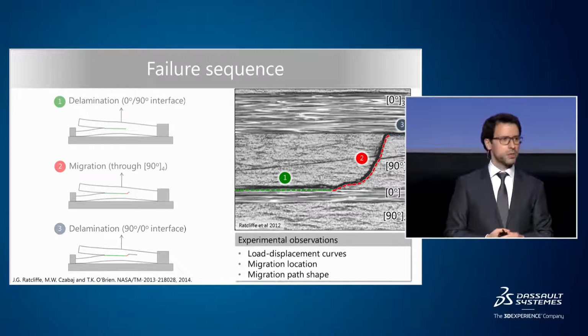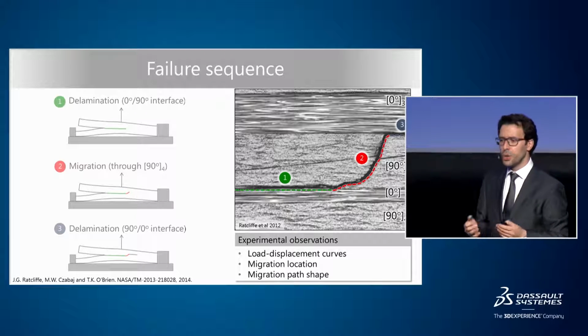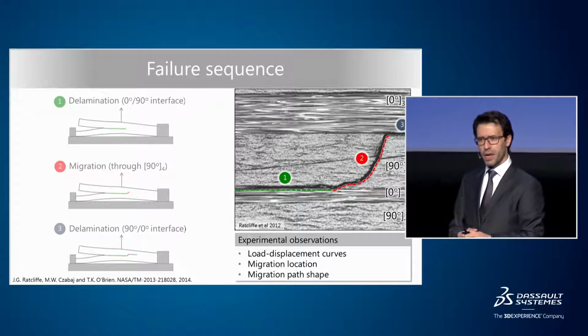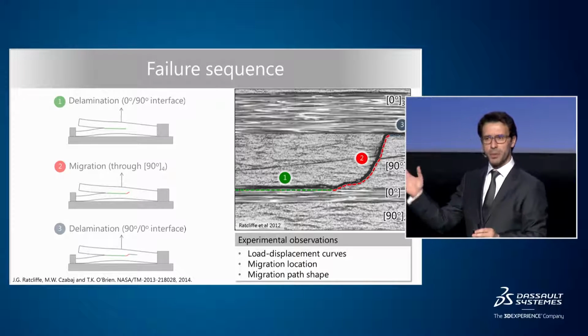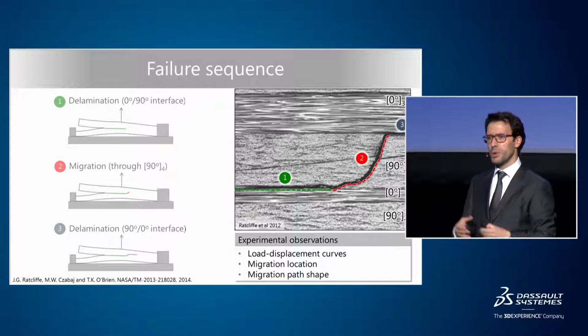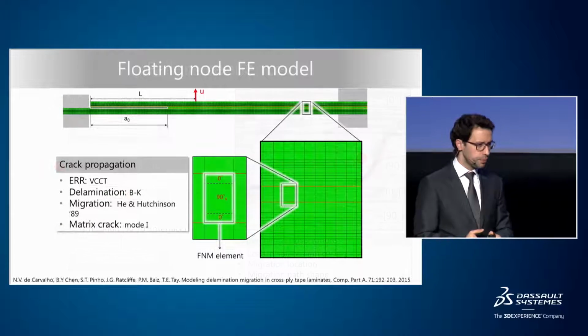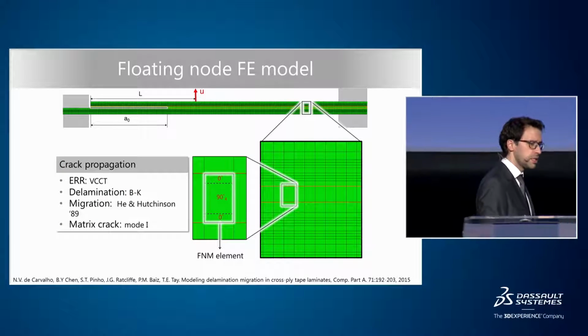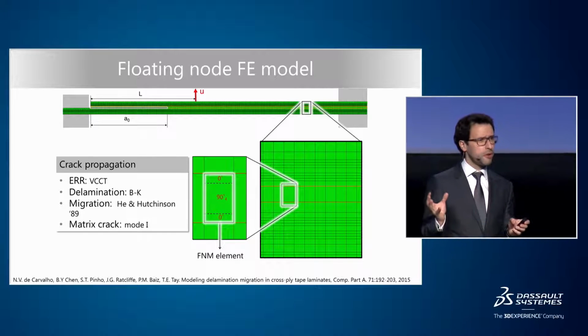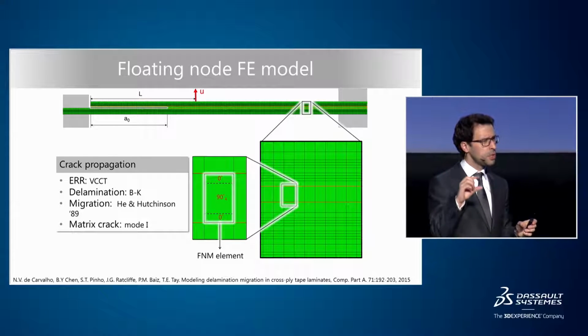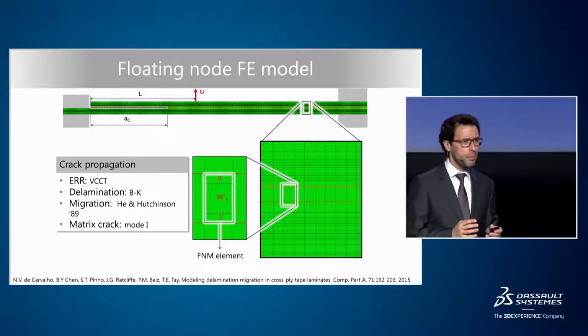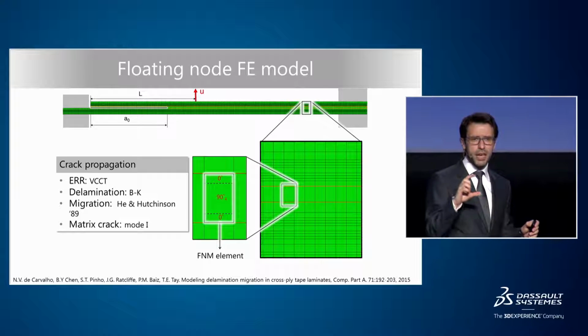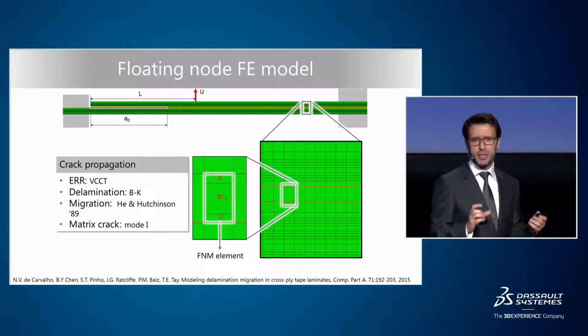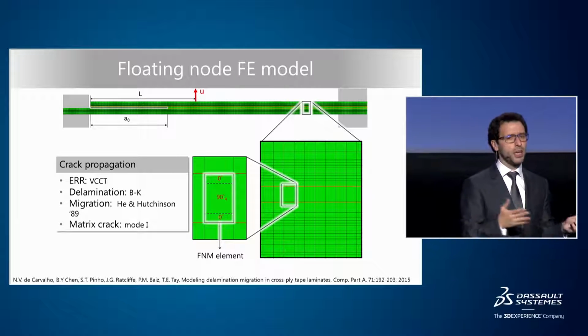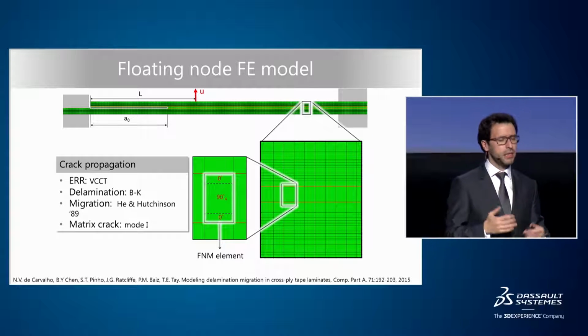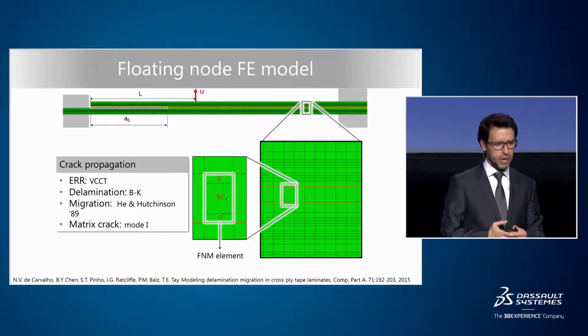So what James and his co-authors measured at NASA were the load displacement curves, the location for crack migration, and also the shape of the crack path. So all of those are things that we want to try to replicate numerically. So we've built a numerical model of this specimen, and because we have floating degrees of freedom, we can use them to simulate these 0, 90, and 0-degree plies where all the action happens, which means that inside our element we have information about the 3 different plies simultaneously, which we can use to define criteria for whether or not those cracks should propagate, as well as for then simulating the propagation of these cracks.